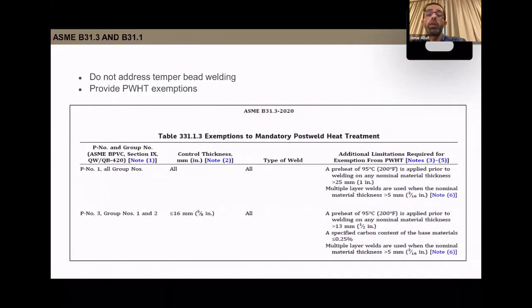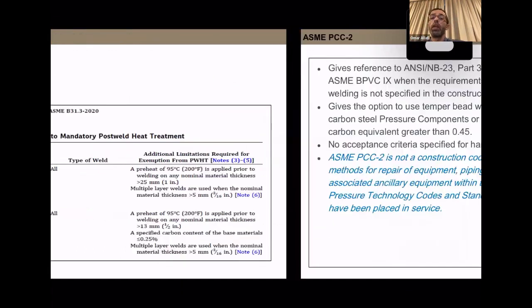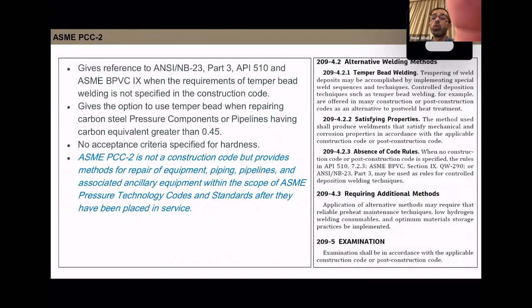In B31.3 and B31.1, they do not address temper bead welding. They provide PWHT exemption by preheat. And PCC-2, although it is a non-construction code, provides a method of repair of equipment and gives the option to use temper bead when repairing carbon steel pressure components or pipeline having carbon equivalent greater than 0.45. No acceptance criteria for hardness. It gives reference to Section IX when the requirement of temper bead is not specified in the construction code.